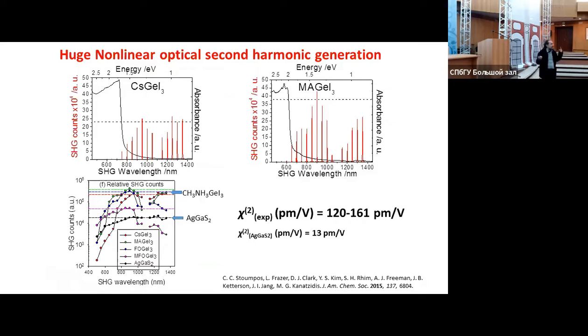But the important property of the germanium perovskite is not its optoelectronic properties, rather the fact that it lacks an inversion symmetry. And this lack of inversion symmetry can be established by second harmonic generation measurement, which shows that it has a very strong response. And if you compare with a known material like silver gallium sulfide, you get a polarizability coefficient, a Chi2 coefficient, which is approximately 1 order of magnitude higher than common materials. So this is the big benefit in this material.